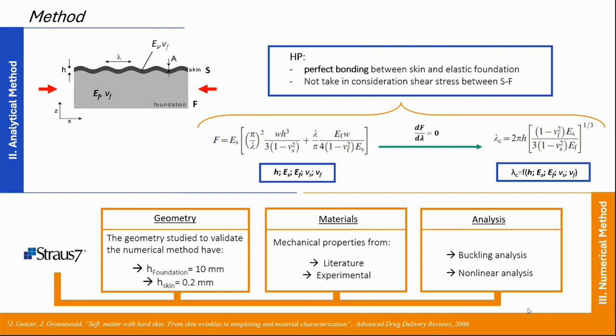The compressive force in the skin is given by the first formula on the left. Lambda denotes the sinusoidal deflection profile of the skin along the direction of the applied force, acting on the elastic foundation. Critical wavelength is observed when the load exceeds the critical value. The wavelength prediction method shows that the critical value for lambda is independent of stress and strain and only depends on the material characteristics and the skin thickness.